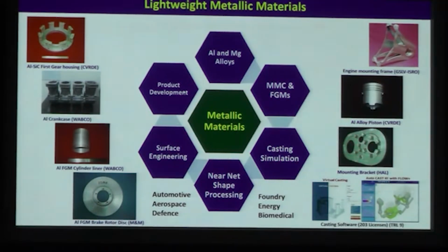When we centrifugally cast it, the density of silicon is less, and so it goes to the interior periphery, and thus the tribological properties and strength can be improved, mostly the tribological requirements, because when the piston is moving in the bore of the cylinder liner, the wear has to be less, and the temperature which is being generated has to be dissipated quickly. That's a functionally graded component.